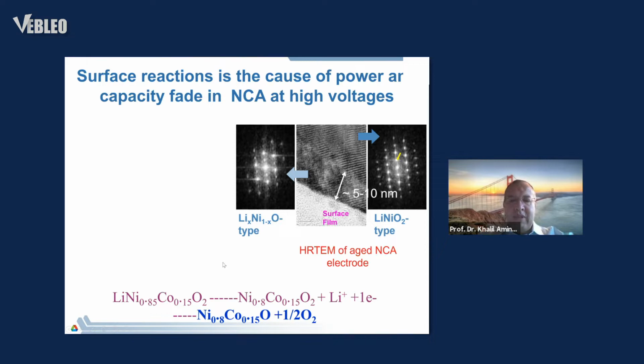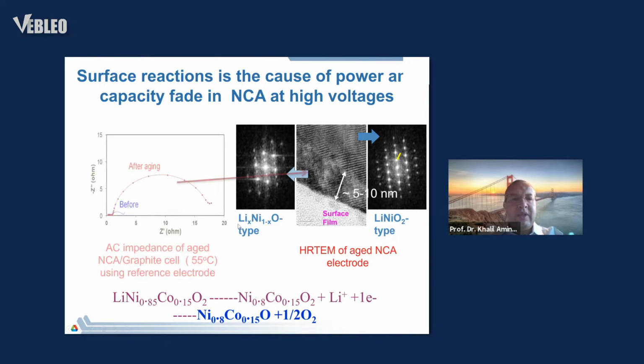So what happens is that when you remove lithium from this nickel-rich material, nickel 4+ in an oxide phase is thermodynamically unstable. So you have an immediate reduction, you form nickel oxide. That's the phase we've seen here by electron diffraction. And then you have oxygen release that reacts with the electrolyte and forms this surface film. So the consequence of this phenomenon is a significant increase in the interfacial impedance of the cell, and that causes the failure or capacity fade that we've seen.